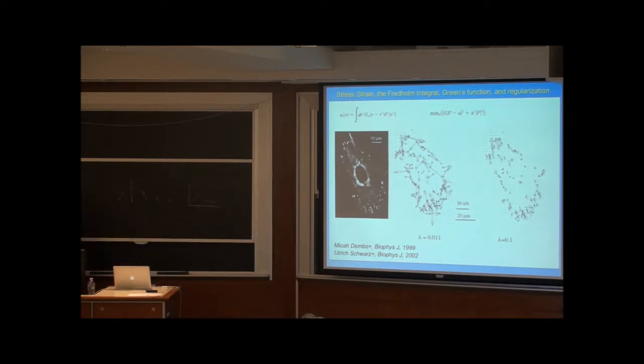But the reality is that when you do these measurements, there's always noise. You never perfectly find where the bead is because of optical noise, and the bead doesn't always move perfectly because nothing is a perfect material. Okay? So what your actual strains will be is some delta off of that position, right? And that's the noise. So now the data that you have looks like this, right? It's not a perfectly smooth strain map.